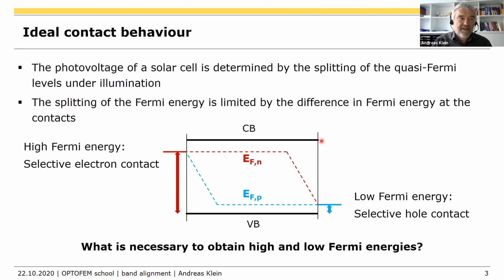contact selective. In a silicon solar cell where you have a PN diode, this is not necessary because the material itself is forming the selectivity, and that's because of the diffusion length. So if you do illumination from this side, you will have the photo-generated holes deep in, the photo-generated electrons, in principle, you hardly have any of them at the back contact, and you will hardly have any holes at the front contact because you have a very high electron concentration here. So then it's the doping and the nature of the PN junction which makes the contact selective for the PN diode. So that's kind of a different thing.